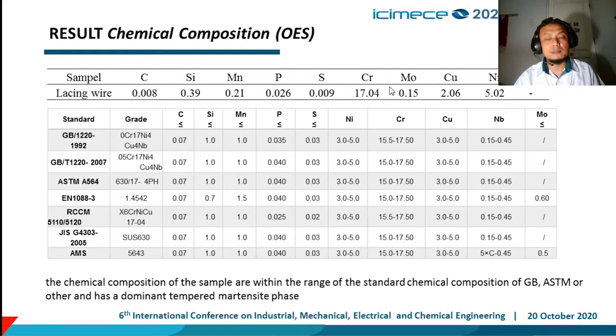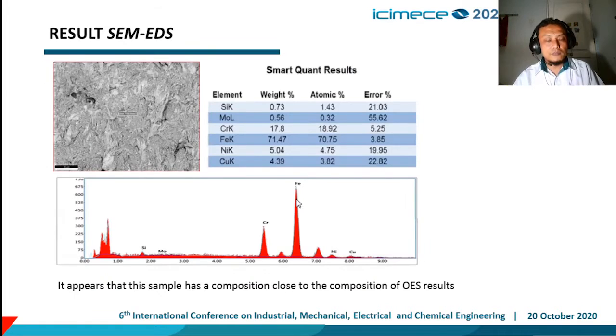You can see chromium 17.04. Under the check using SEM and EDS, it appears that this sample has a composition close to the composition of the OES results.